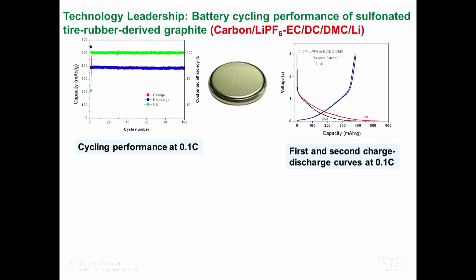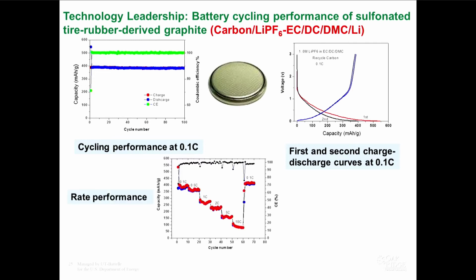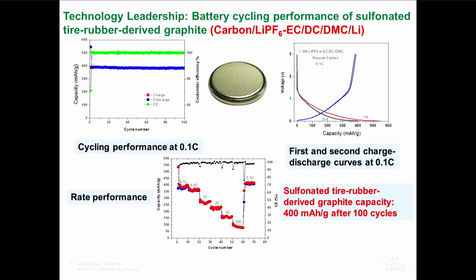So you can see the first, second charge discharge curves, and you can see again the voltage drop, I'll talk about it in the next few view graphs, and capacity drops after a few cycles, but it's holding steady. And the rate performance, we have done it at different Cs, 5C and also 10C, the capacities are still high. So there is an opportunity for this sulfonated tire-derived graphite, you can run it at slightly higher capacity. To summarize this technology, the sulfonated tire rubber derived graphite has 400 milliamp hour per gram after 100 cycles. So we have shown the technology is either equal or better than the commercial graphite.